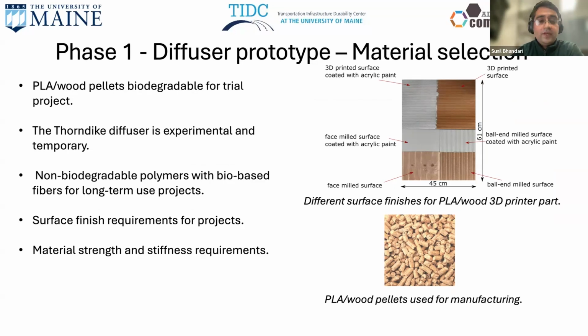And for a 3D printed part, we can do post-processing, CNC machining, to get different surface finishes. But for these diffuser projects, we deemed the as-printed 3D printed surface shown here acceptable. And there are also material strength and stiffness requirements, so the manufactured part with these materials can withstand the loads. For this project, the strength and stiffness offered by PLA wood polymer was considered sufficient.